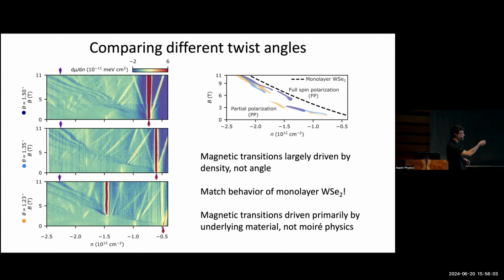And in fact, we've also measured monolayer tungsten diselenide. Those states as well undergo magnetic phase transitions, and you can see that the carrier density at which those magnetic transitions occur matches really closely to what we see in the Moiré systems. So what this seems to be indicating is that at least for this range of twist angles, it's not the Moiré superlattice which is dictating where specifically the magnetic transitions occur. Rather, it's the underlying material properties, that is the density in this twisted tungsten diselenide, which is telling us when you're going to be magnetic or not. And then that in turn has some huge effect on the nature of correlated states.